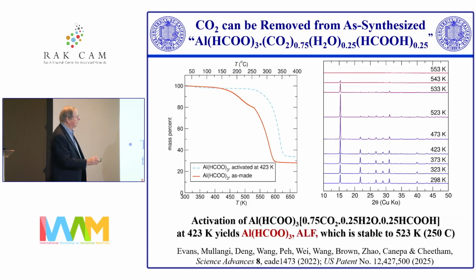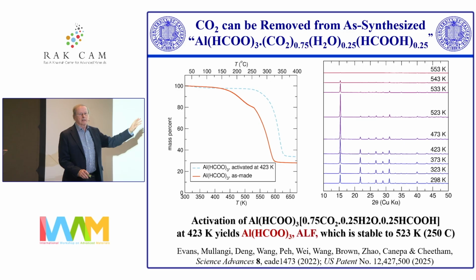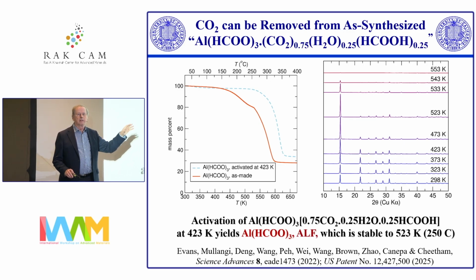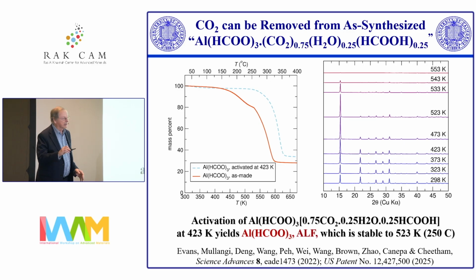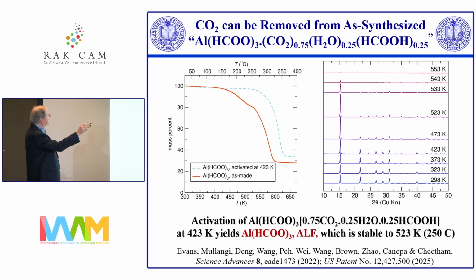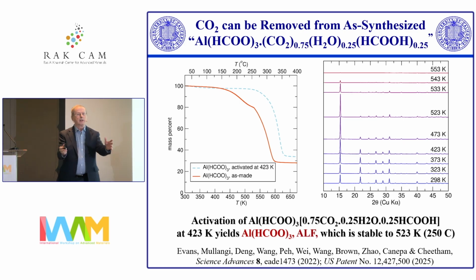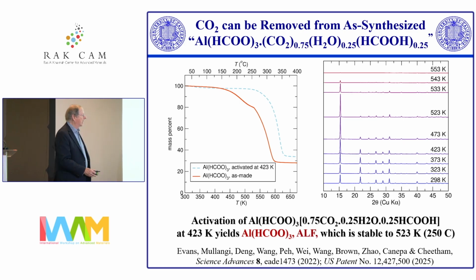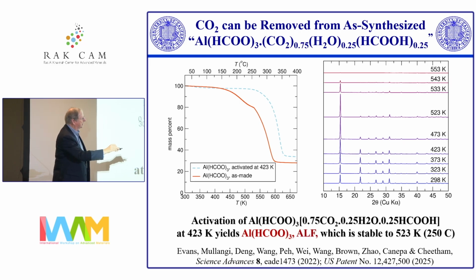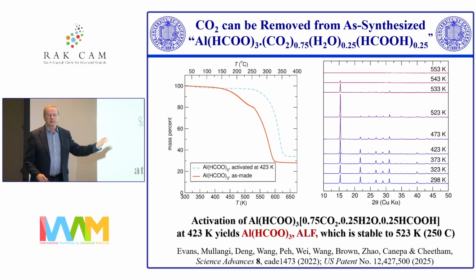So we looked at this activation process with aluminum. Being an old zeolite chemist, I knew that aluminum was a much better bet than iron because it won't have any redox properties. And so we showed that you can activate the aluminum formate and remove the CO2 from the cavity. And you end up with a porous MOF then. And this porous MOF is stable up to about 250 degrees C. This is just the activated material. And the composition that I'm showing here is the composition that was reported by the Chinese group.